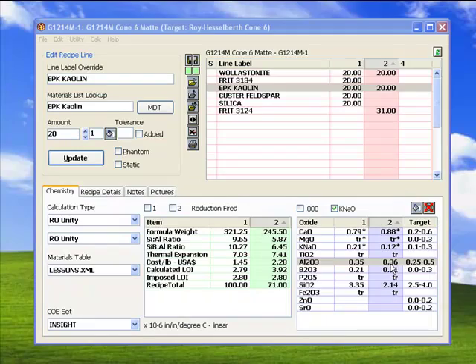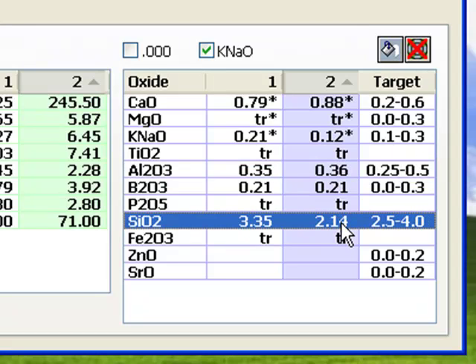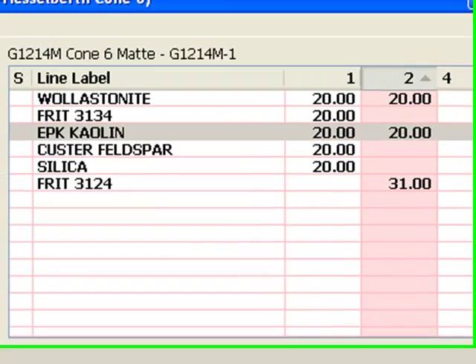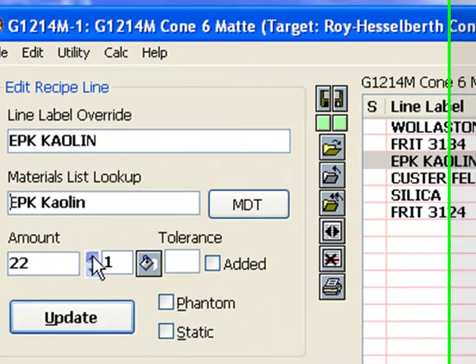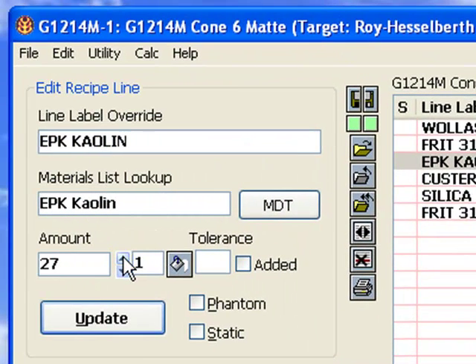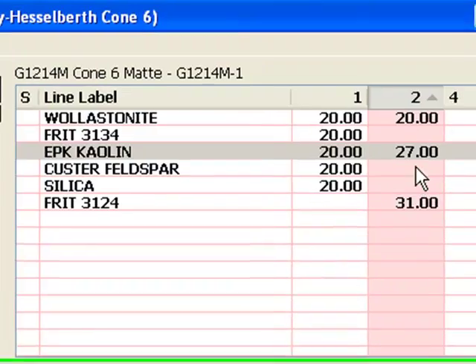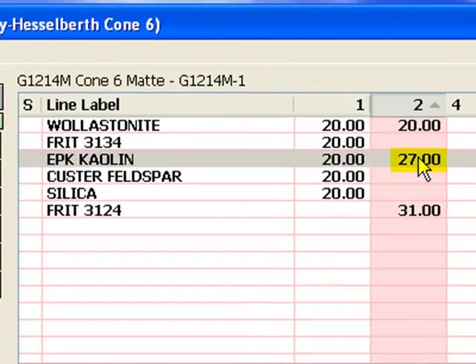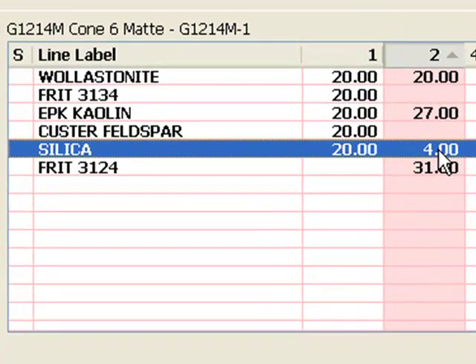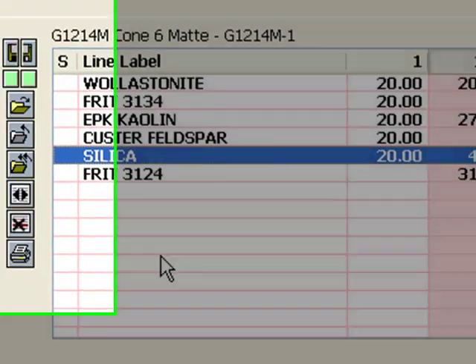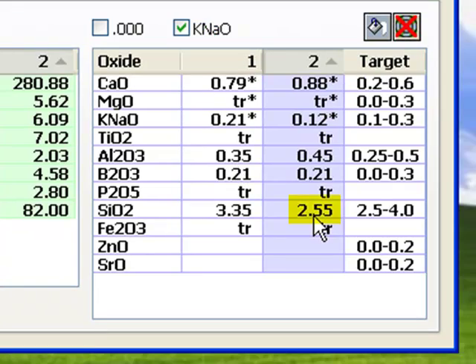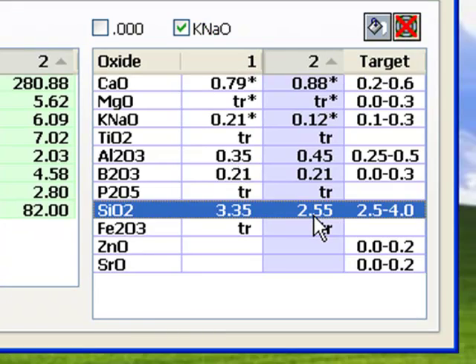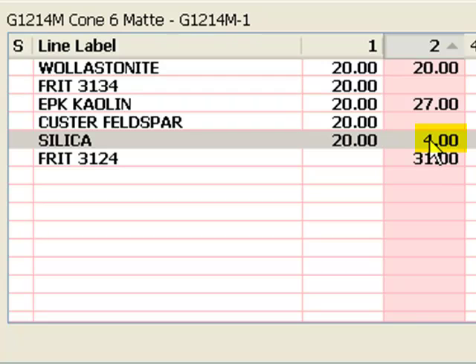That took the Al2O3 in G1214M recipe to 0.36. I'm targeting at least 0.45. The silica should be the minimum 2.5 target. That gives the silica to alumina ratio of 5.5. So I selected the kaolin line in Recipe 2 and clicked the increment button until the alumina for Recipe 2 reached 0.45. This took the kaolin to 27. I've selected the silica line for Recipe 2 and nudged it up until the SiO2 reached 2.5. This turned out to be 4.0 silica. Later, this bit of silica in the recipe will make it easy to fine-tune the amount of gloss.